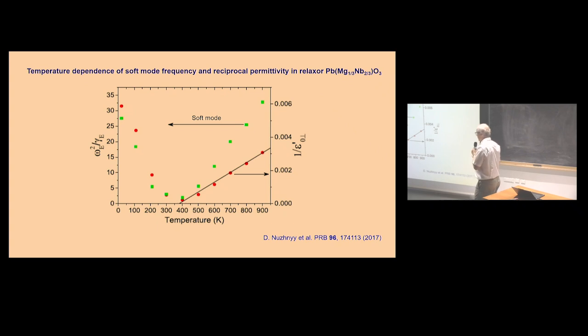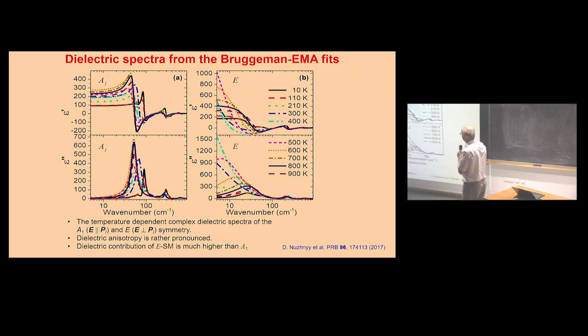So in this case, we have a ferroelectric soft mode within polar nanoclusters, and then you have dynamics of polar clusters below 600 Kelvin, which also is responsible for the broad dielectric anomaly and much higher permittivity at low temperatures. Now I have to stress that in this case the phonon contribution is just less than 1,000, or in this direction only less than 300, while you saw before that the peak permittivity around 250 Kelvin is 20,000. So dielectric relaxation is much stronger.